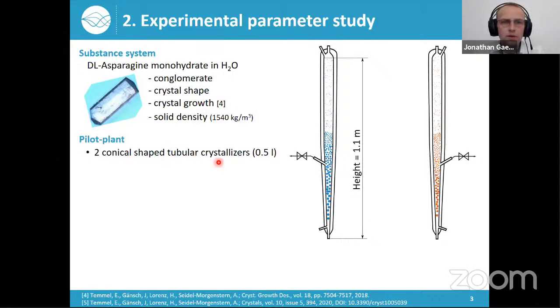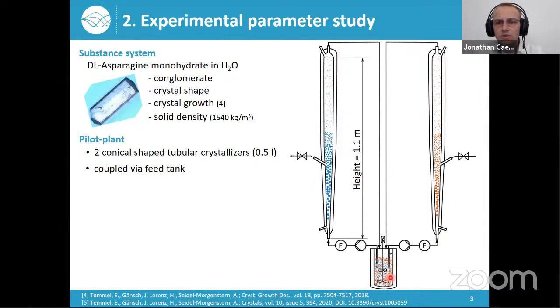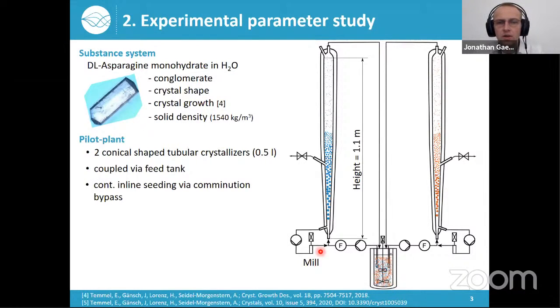Our pilot line now consists of 2 of these tubular crystallizers because we want to separate both enantiomers from each other at the same time. These crystallizers are coupled via a feed tank, which contains our racemic feed solution and some racemic excess. And the continuous seeding is realized using this milling bypass. So how it works: our large enantiopure crystals are withdrawn here and sent to the high-speed disperser, our mills, where they get crushed. And the enantiopure fragments we send back to the process as our new seed material.